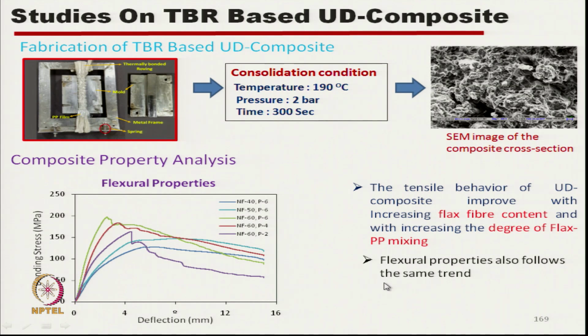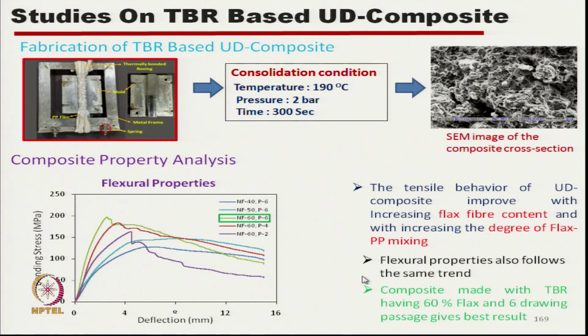The flexural property also shows a similar trend: with the increase in the natural fiber component and with the increase in number of passages, the flexural strength, the bending stress, increases. And if we see the green bar, this is natural fiber component 60 and passage 6, which is giving the highest bending stress. So, the composite made with thermally bonded roving having 60% flax and 6 drawing passages shows the best result.